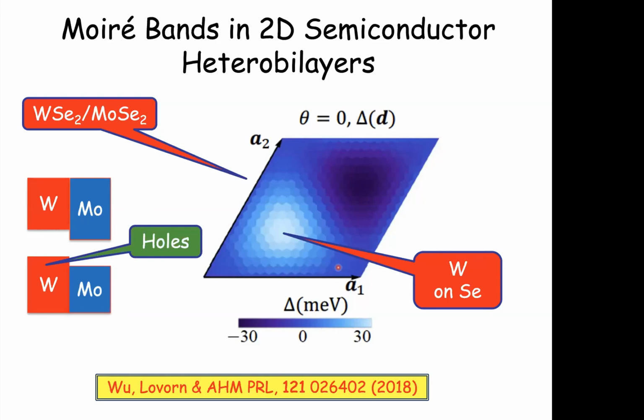But in addition to that, there is clear particle-hole asymmetry in the ab initio calculations, in which the separation to the remote bands is smaller on the valence band side than on the conduction band side. And the observation that Stephen Carr explained to me is that that effect is captured by a simple two-center approximation in which you imagine the tunneling between pi orbitals just depends on the distance between them, let's say.